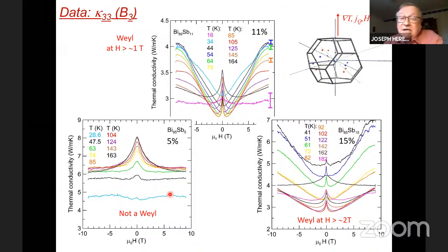It is immediately striking that the samples that don't have trivial pockets have this very large increase in thermal conductivity that you don't see at 16 Kelvin because, of course, there the thermal conductivity is completely dominated by the lattice. But it appears around 35 Kelvin or thereabouts, and it's actually really maximum in the 40 to 120, 140 Kelvin range. It's still there at 160 Kelvin. There's still even a hint of this positive thermal conduction at 200 Kelvin. Same thing in the 15% sample.